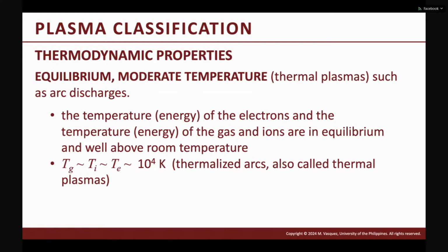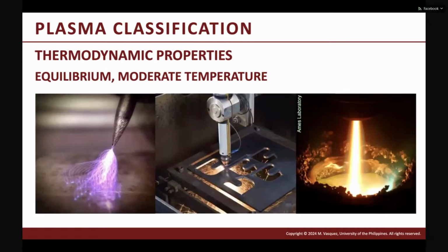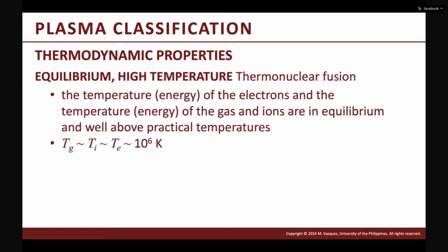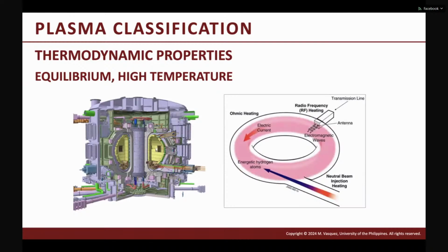Now, the second type of plasma is equilibrium, moderate temperature plasmas or thermal plasmas. This is where you have extreme or hot arc discharges. And here, the gas temperature, ion temperature, and electron temperature are equal. You find this in, for example, welding or plasma cutters, and even in plasma gasifiers. The temperatures here are in the thousands of Kelvin. Now, the third type is the equilibrium high temperature plasma. This is where thermonuclear fusion happens, and everything is in equilibrium and at very high temperature, that's 10 to the 6 Kelvin. So this is the plasma generated in a fusion reactor, for example. They try to get temperatures similar to the temperatures on the surface of the sun.